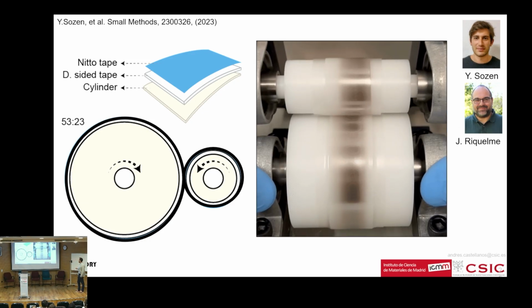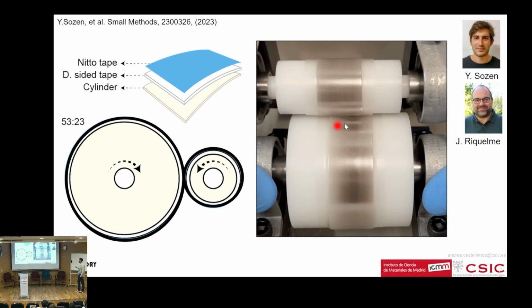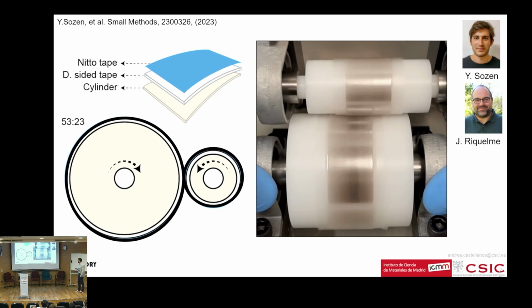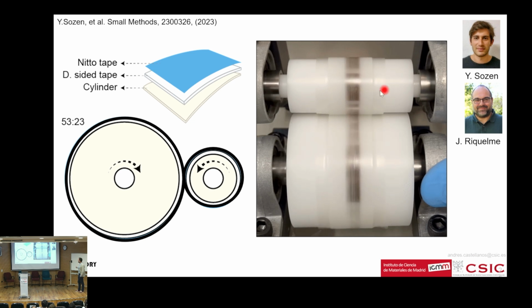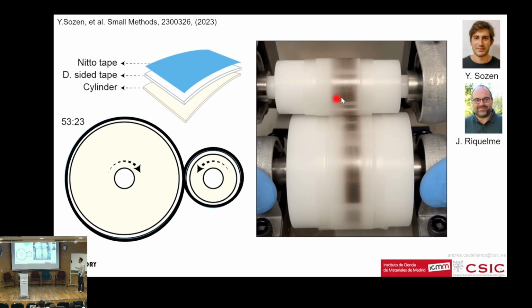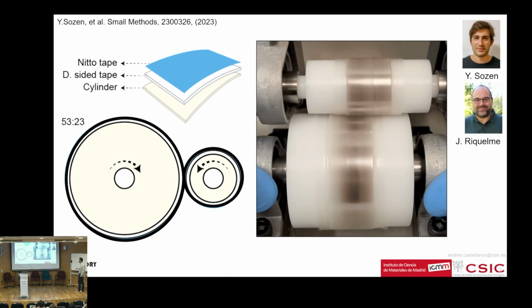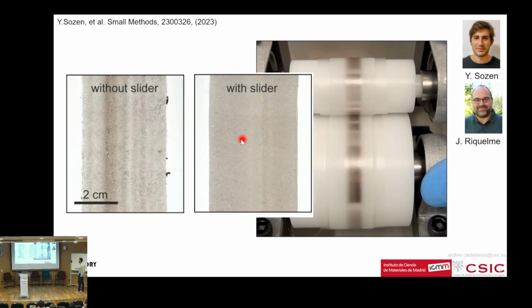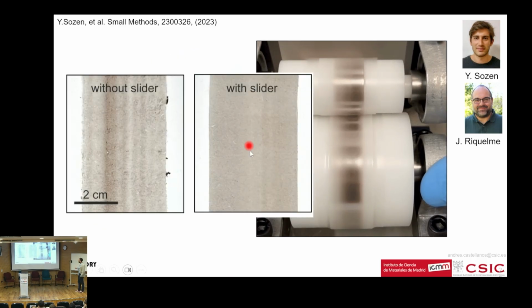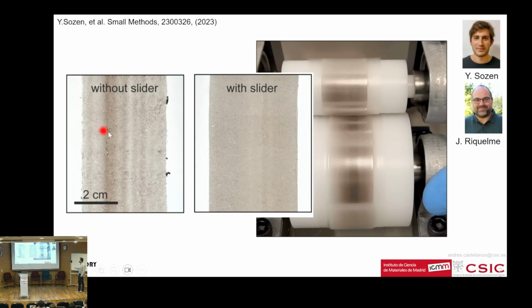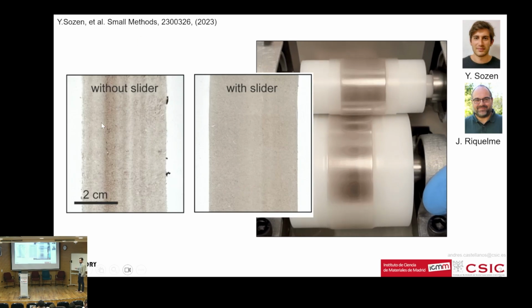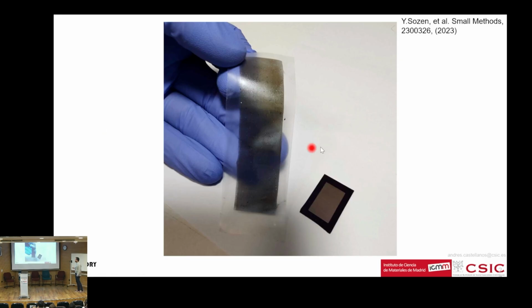When you do the rolling, you start getting crystals being cleaved and spread out all over the tape. We included this lateral sliding stage in order to get it even more homogeneous along this axis of the tape. If you take a look at the tape, it looks like this. These parts are crystallites of van der Waals materials being exfoliated. Without the slider, you get these kinds of fringes. When you finish the roll-to-roll exfoliation, you get the tape, and this is a film full of crystals that have been exfoliated from the parent flake.